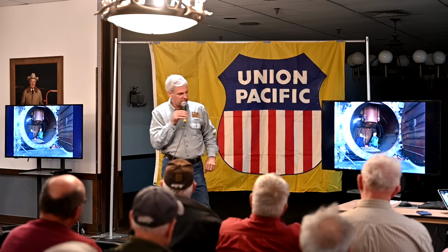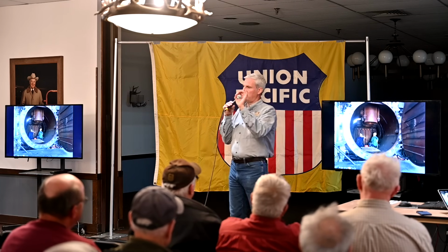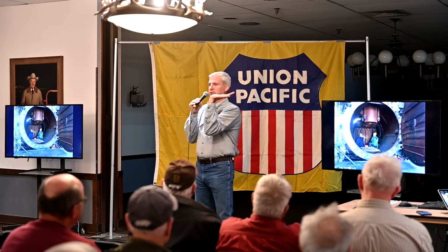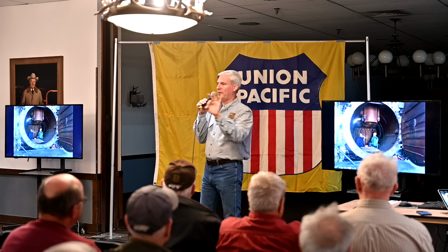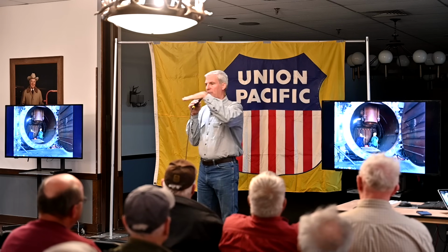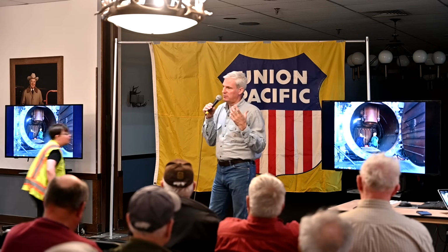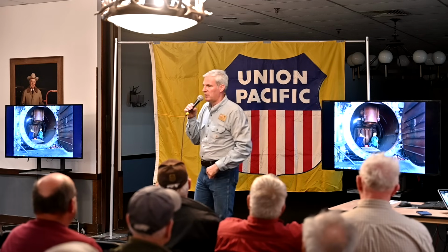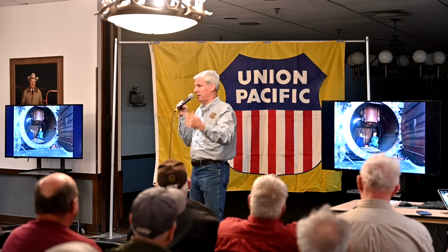One test in particular is called a bend test. So you take this test specimen of a specific dimension and you fold it over on itself. So imagine a piece of Play-Doh, a cylindrical piece of Play-Doh, and you flop it over like a wet noodle. Well, you take a machine that has the capacity to flop that piece of steel over, and it has to pass that test with no deformation, no cracking, no breaking.